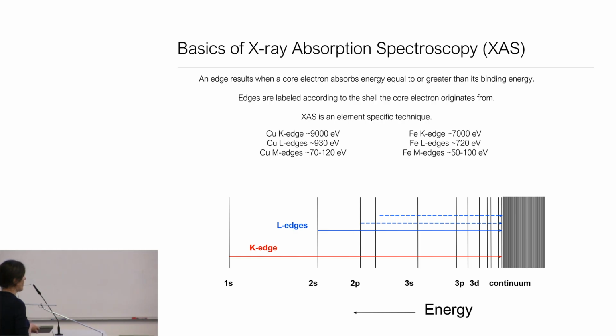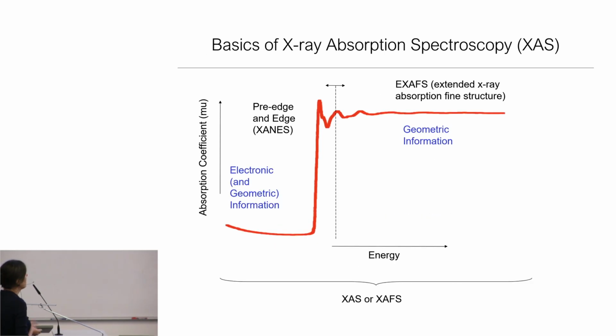Okay, with that understood, let's take a look at standard X-ray absorption data that would be something you might get straight off of the beamline. What we're monitoring here is the absorption function mu as a function of energy. This would be a typical X-ray absorption edge, and we typically divide it into two regions: the edge or XANES region, where we largely get electronic and geometric information, and the EXAFS, or extended X-ray absorption fine structure region, where we largely get metrical information about what surrounds that photoabsorbing atom.